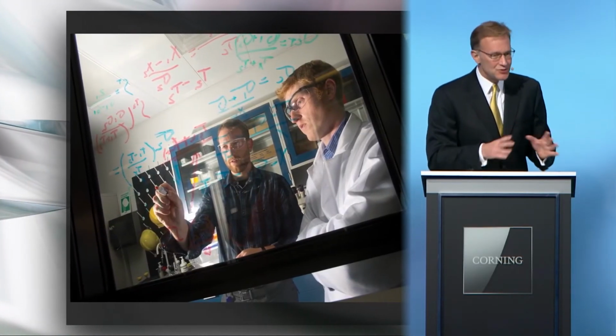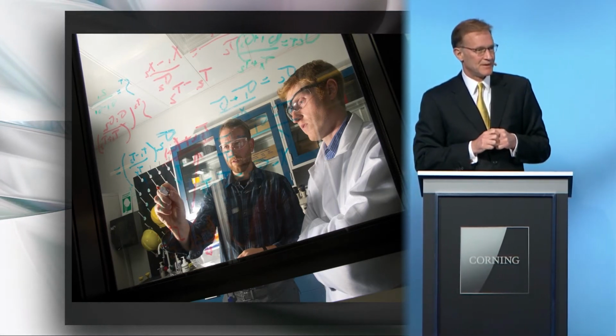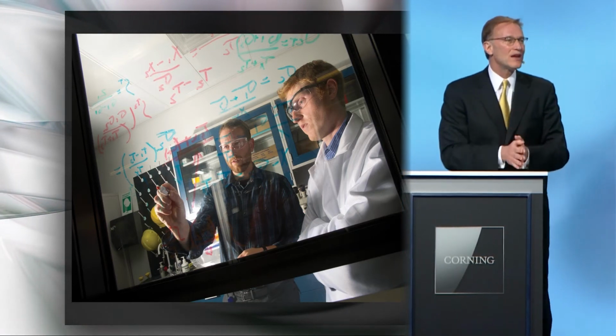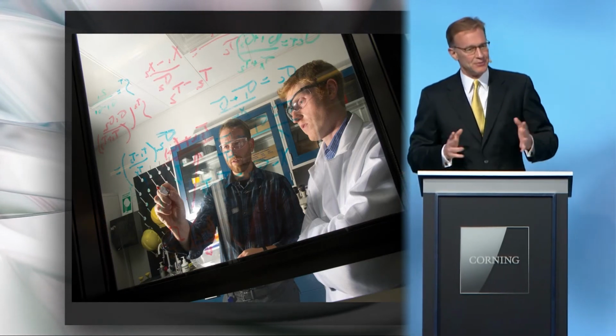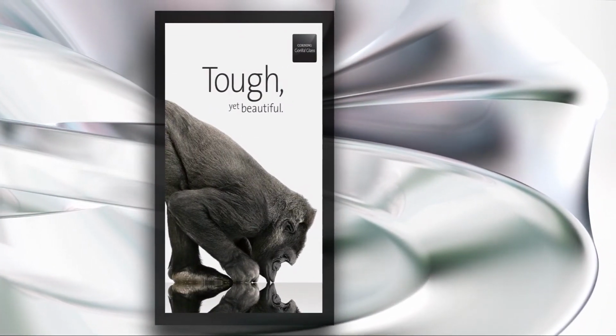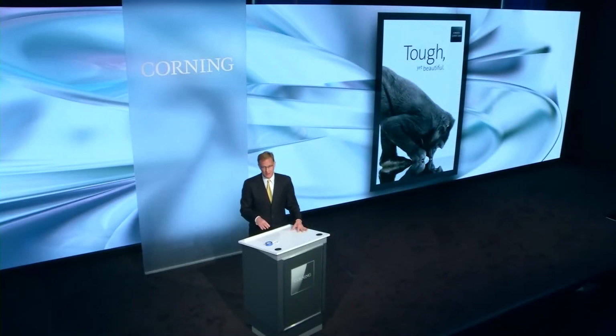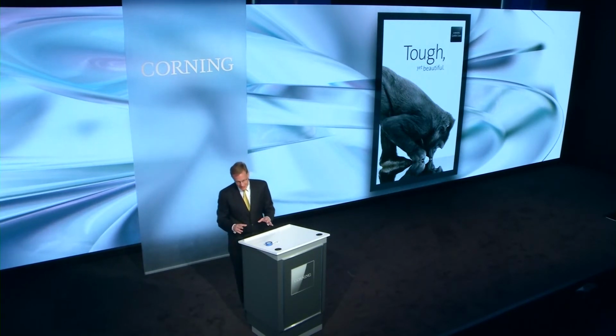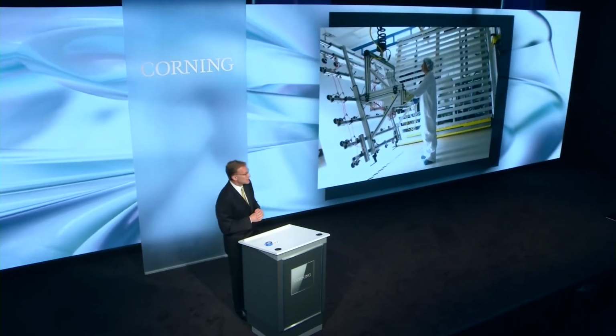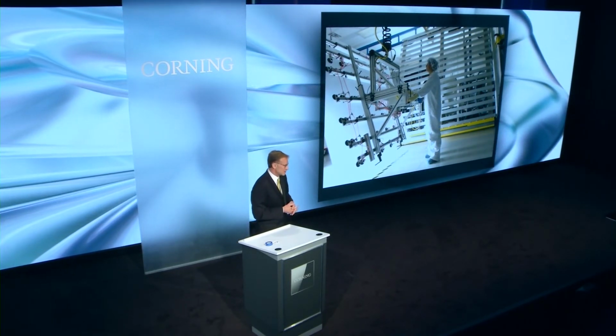Corning had experimented with damage-resistant glass in the 1960s, so we started by drawing on that knowledge. We then developed more than 100 new glass compositions before we felt like we had one with the right attributes. But developing the composition was just the first hurdle. When we learned how much glass Apple required, we realized we needed a scalable manufacturing platform instead of the small specialty tanks we originally had in our minds. So we repurposed our fusion assets with a few engineering modifications for the unique forming characteristics of the new glass.